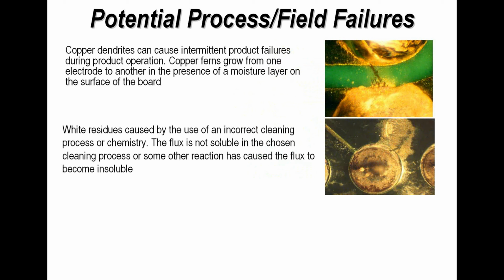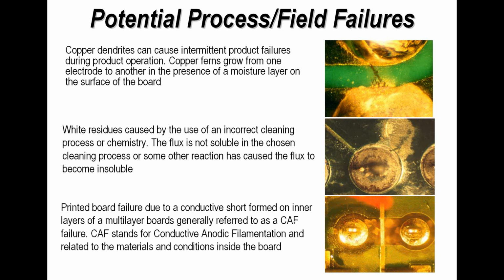Another example is white residues and corrosion products on the surface of a printed circuit board. Again, white residues quite often are not harmful for the product, but if it's a combination of the white residues and the dendrite formation, then clearly this may be an issue. CAF is another failure mode which can happen in a printed circuit board assembly, but this is an internal defect, and certainly conformal coating would not necessarily stop it happening.